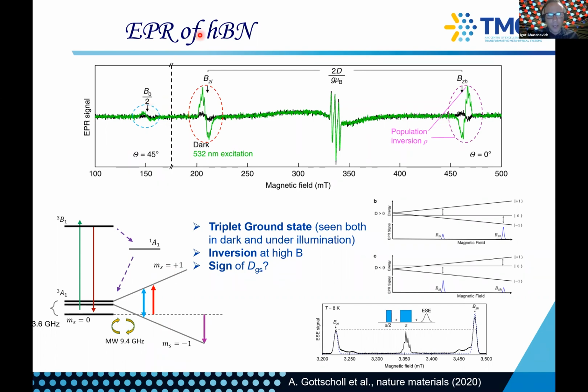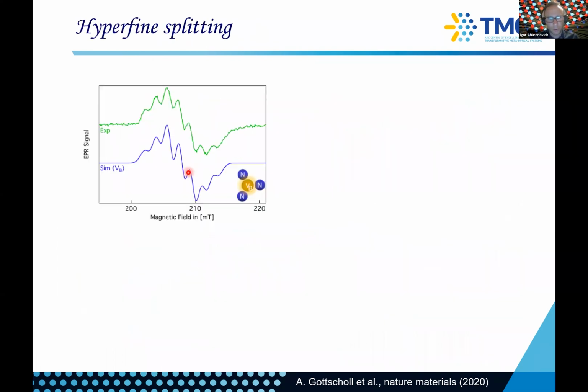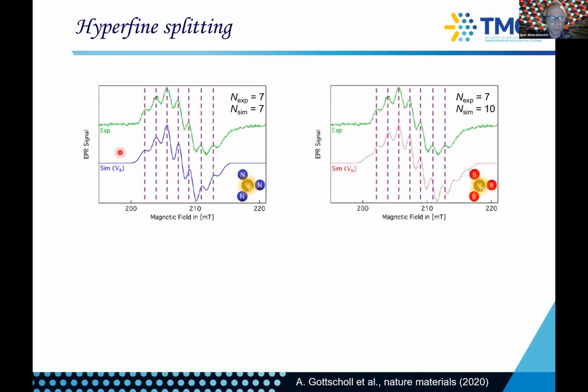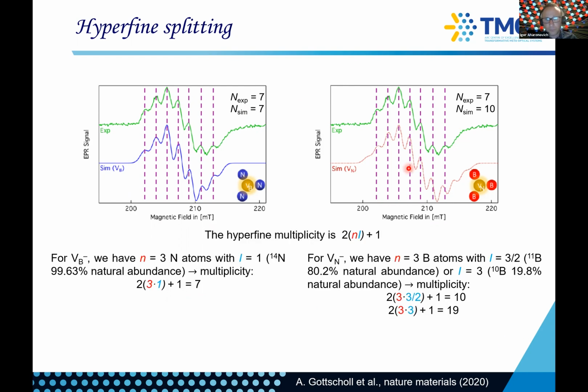The EPR is only available because we could make an ensemble, 10 to the 17, 10 to the 18 spins. So a very large number of spins within an hBN crystal. Now, the other thing you can learn from EPR and ODMR is the hyperfine splitting. This really tells you precisely what the defect is. This is the experimental verification. This is our hyperfine splitting in EPR, and this is the simulated VB. So this is a missing boron surrounded by 3 nitrogens. And you can see here 7 peaks, matches perfectly. If you had put a missing nitrogen with 3 borons, you would have had a very different spectra here. So it's very clearly a negatively charged boron vacancy.